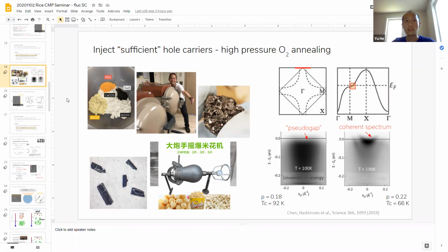On the other hand, when we do photoemission, we can do ozone surface treatment. So in this case, it's no longer a bulk doping, but we can selectively just heavily oxidize the surface. Some of these preliminary data shown by the Brookhaven group, they can reach, I think, 29 or 30% doping, where superconductivity is killed. The problem with those type of surface treatment is that you can't really have intrinsic measurement of TC. So it all comes from a guesstimation of the measured gap and Fermi surface volume.